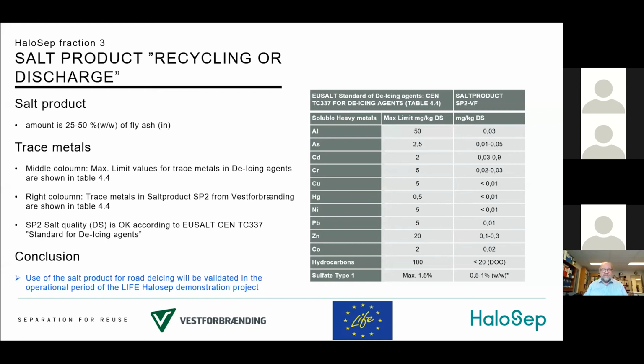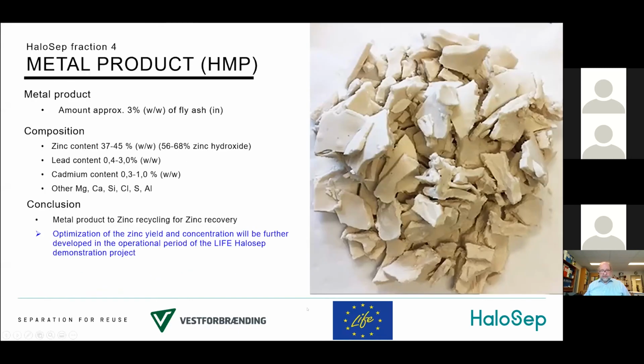And the next, please. The metal product is about 3% of the incoming fly ash. The zinc content is 37 to 45%, corresponding to up to 68% zinc hydroxide. It has a lead content of up to 3% and a cadmium content up to 1%, and then there are other inerts. The metal product will be sent out to zinc recycling outside the plant for zinc recovery. The optimization of the zinc yield and concentration will be further developed in the operational period of the LIFE HaloSep demonstration project. Next, please.